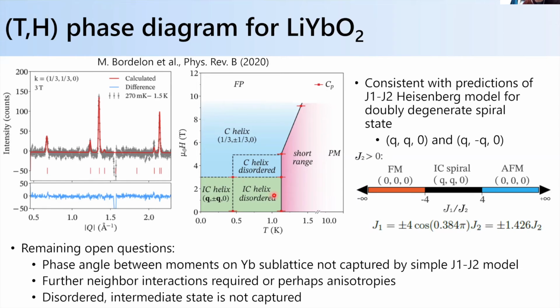Basically, as you cool down under 0 field, there's what we call a disordered helix phase into the ordered helix phase. And then as you apply a magnetic field, it locks into this q,q,0 type wave vector. And so what Leon Balents and his student Chenchao Liu did is they used this J1, J2 model to try and determine what the ground state should be.